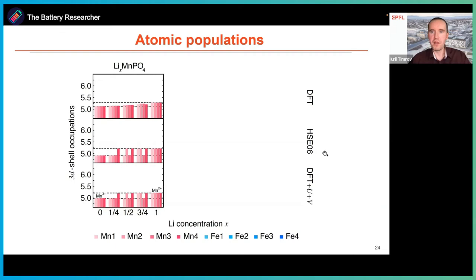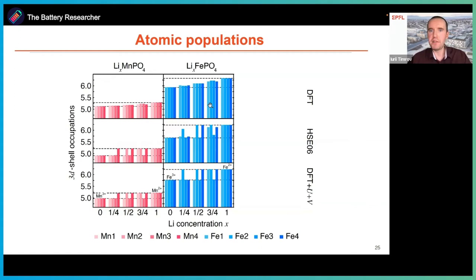In the case of iron, if we do exactly the same analysis, we again observe that DFT fails because occupations change on average equally, which is not correct. While hybrid HSE06 sort of tries to show the digital change in occupations, it's not very accurate, as you can see. Instead, DFT+U+V still works very well and very clearly shows digital change in the occupations.